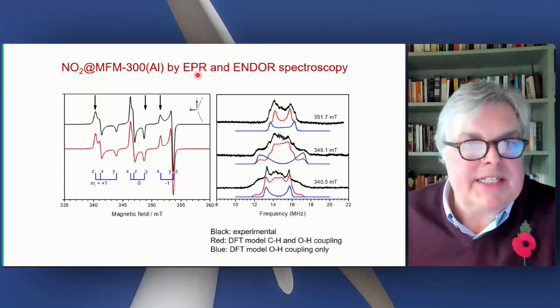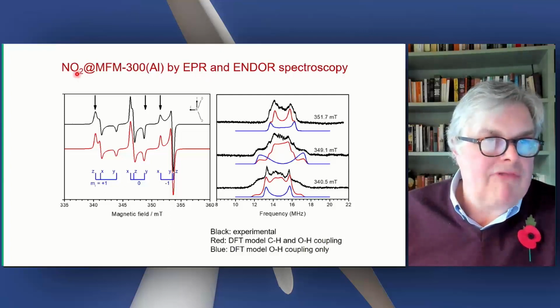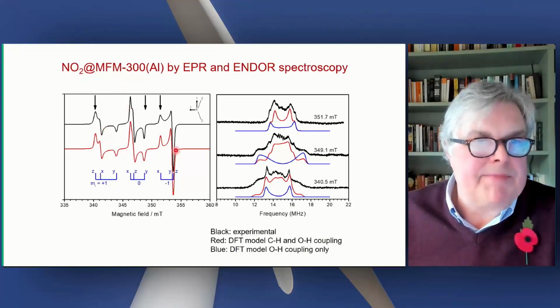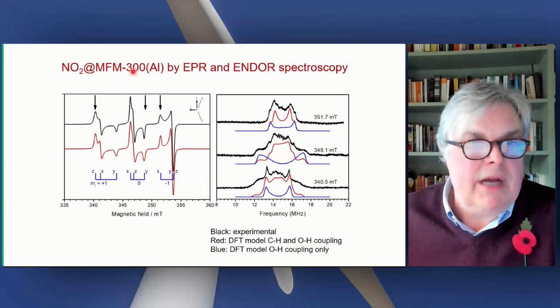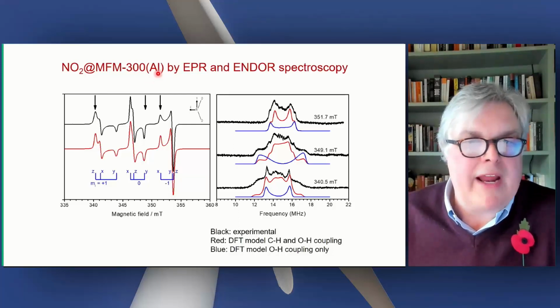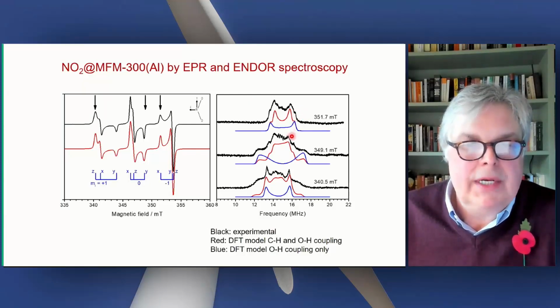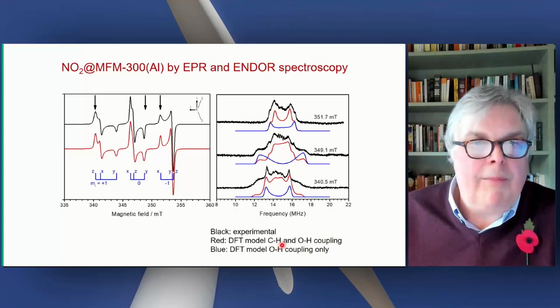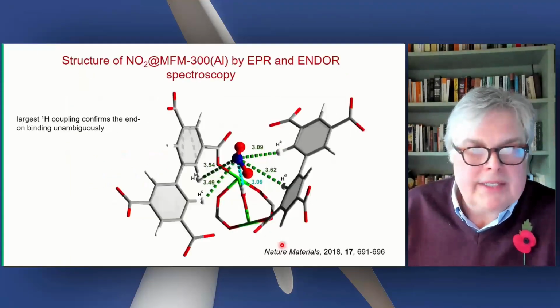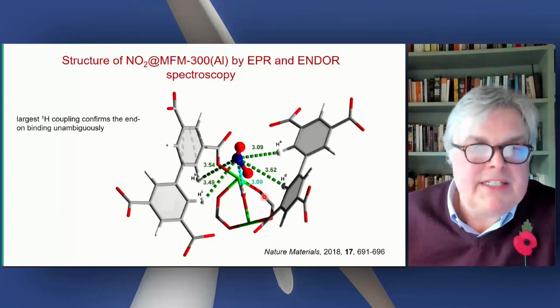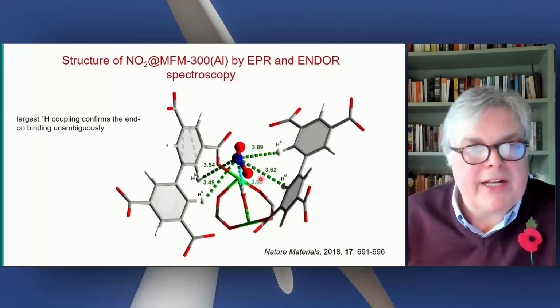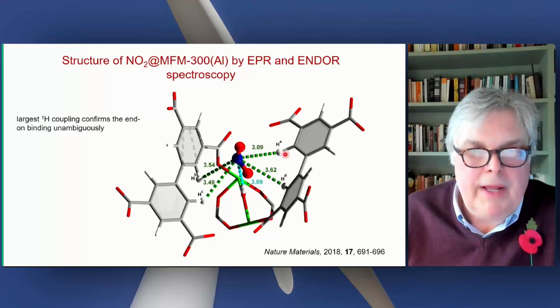We can also analyze this by EPR and ENDOR spectroscopy. NO2 is a radical, it has a single electron. This is the EPR spectrum of NO2 within this aluminium MOF, which is diamagnetic, so there is no spin on the aluminium or on the framework. We link that to ENDOR. This is mixed EPR and NMR spectroscopy that analyzes the interactions between the nitrogen radical and the CH, the H protons on the phenyl groups, linked to DFT modeling with or without coupling to the OH and the CH groups. And purely from the EPR and ENDOR spectroscopy, we can simulate the structure which is shown here. And it is precisely the same structure as we see by neutron and powder X-ray diffraction, NO2 interacting with the OH group and the 4 CH groups.